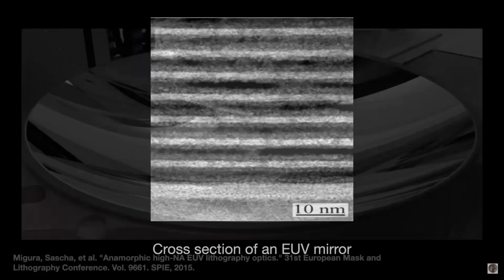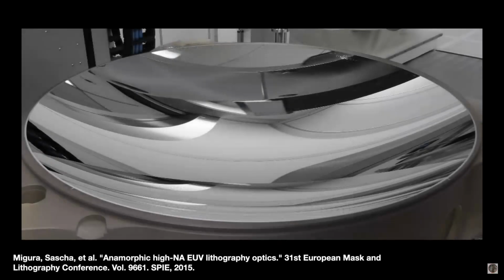Even with all that, the multi-layer mirror's maximum reflectivity is just about 70%, with the rest of the energy absorbed as heat. And even that performance can only be achieved in theory. In practice, interactions between the materials will hurt reflections. For example, the molybdenum layers are crystalline, while the silicon layers are amorphous, non-crystal structures.